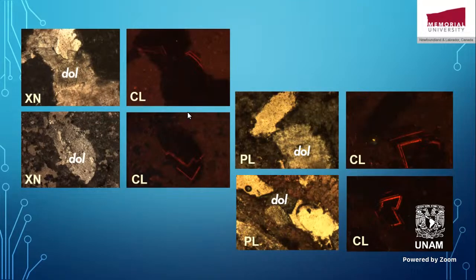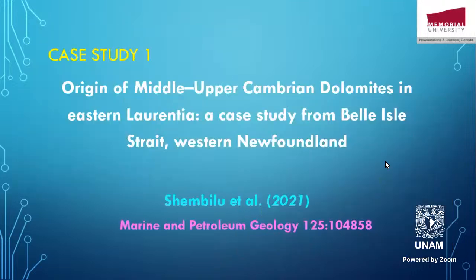Okay, I'm showing you here some examples of the cements under cathode luminescence, and look at the chevron sign, those bright lines like a chevron sign. Here too, and here too. We see them here too, and here. These are characteristic of that dolomite generation that we see here under thin polarized light. Well, this means that these are from different depths in a core, and this tells us that these cements were precipitated by the same diagenetic flow throughout the entire core. It's one phase of sedimentation. They belong to one phase of sedimentation.